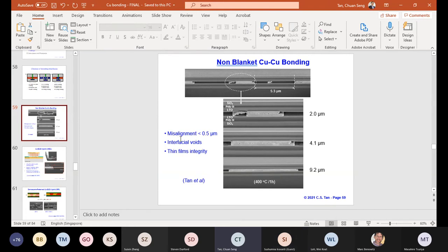On the other hand, the DBI technology, remember, is actually based on oxide to oxide, if you ask me, and then you can do a batch annealing subsequently. Oxide to oxide fusion bonding is a technology that people use to make SOI wafers, and that can be done in a very, very short time, and therefore the throughput can be enhanced. So firstly, there is a gap that you have to worry about. Secondly, it's throughput.